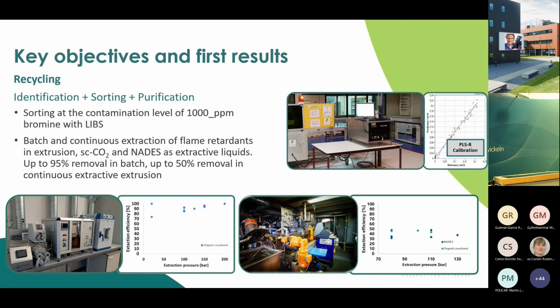For the purification, once we have identified that the material contains brominated flame retardant, we started up, and this is the picture you see on your left, a lab-scale purification system, where we are using a combination of supercritical CO2 and NADES solvent, a so-called green solvent, to extract the brominated flame retardant out of the materials. So we worked with different extraction setups, different solvents, different pressures and temperatures. And as you can see, finally, we reached a removal on a batch reaction of about 95% of the brominated flame retardant out of the different waste streams.